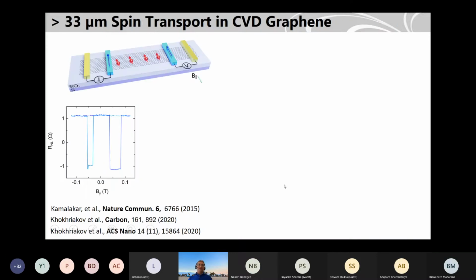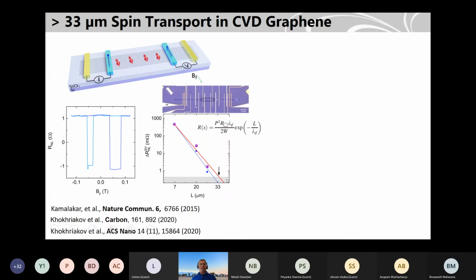Okay, we wanted to further improve that spin transport, and it took a little bit of time because we had to improve the quality of our devices. After 5 years, we could report up to 33 micrometers of spin transport, which is quite good in these devices. This is the schematic again, and the spin valve experiment. This is one example.